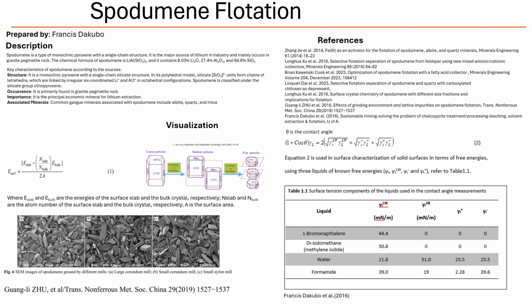Yes, in controlled amounts. The idea is they react with the mineral surface first, kind of priming it, making it more receptive to the collector, attaching strongly and selectively. Like a chemical handshake before the main event. Yeah, something like that. One study showed adding Fe3+ ions really boosted spodumene recovery, but you had to get the dose and the pH just right. Too much or wrong pH, and it might not work or could even start floating the gangue. Tricky balance.